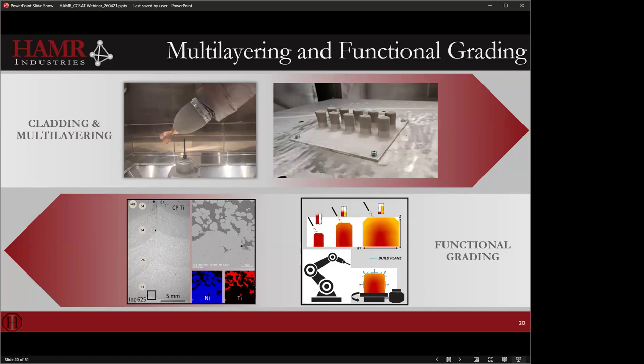So cold spray can build off of any part in any orientation. We aren't worried about melt pools. We aren't worried about gravity or solidification effects. So we can spray in any direction, and we can control what material is where because we're using powder feeding. That allows us to control what material goes where on the part and when. So cold spray is really uniquely, along with powder bed and powder DED, the only other capability that allows you to control what material goes where and when, which allows you to do full, true three-dimensional functional grading.